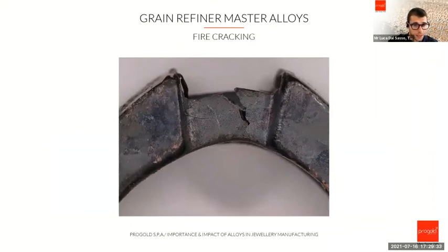And if you look properly, you can also see the border of the grain in which the crack begins. So imagine a large number of small grains: it's very hard to break them because they are really small and their borders are not so extended. So basically, this is a very huge defect, a very common defect in the 18 karat red gold, which can really be eliminated with a grain refiner master alloy.